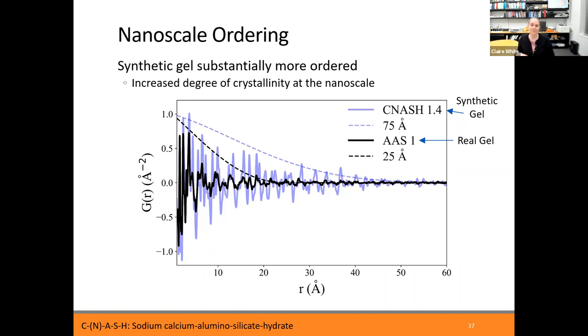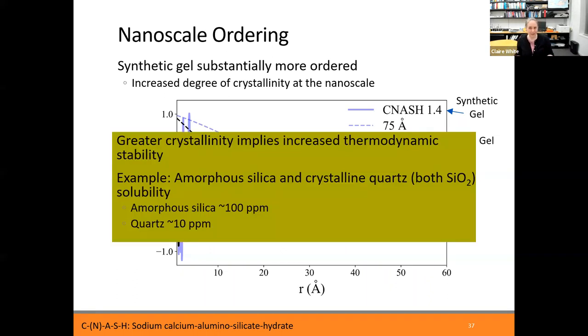So for example, because I know I've kind of twisted this up a bit, let's use an example. Greater crystallinity implies increased thermodynamic stability, and let's use silica as the example here. If you have an amorphous silica versus crystalline quartz, and you look at their solubilities, the amorphous silica is 10 times more soluble compared to the quartz.